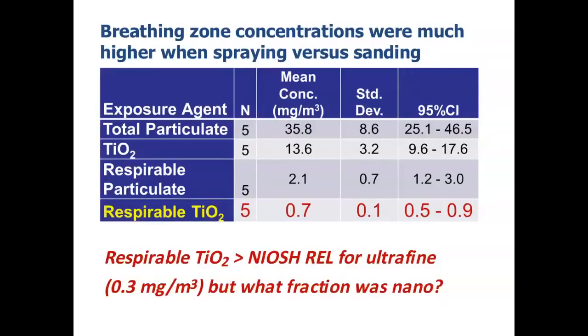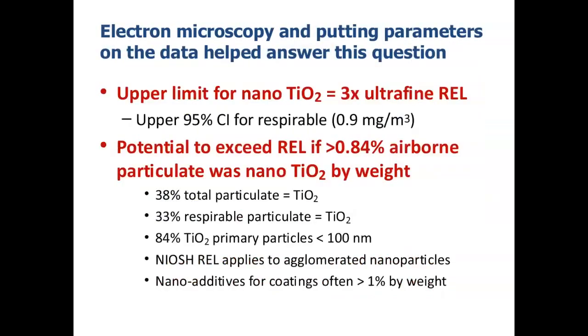Another finding was that breathing zone concentrations were much higher when spraying versus sanding. So the mean concentration of respirable TiO2 shown here was over twice as high as the NIOSH REL for ultrafine TiO2. But an important question is what fraction of the respirable TiO2 was nanoscale. Revisiting the electron microscopy results and putting some parameters on the data helped to answer this question.